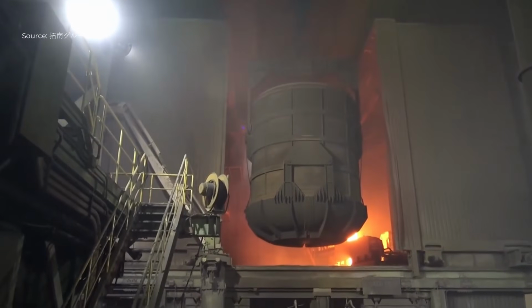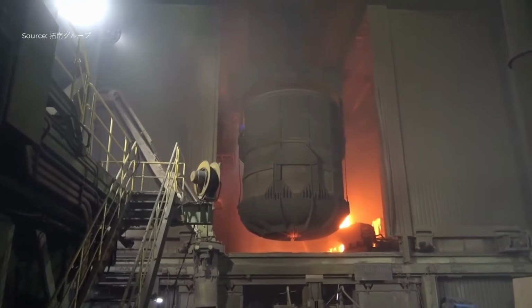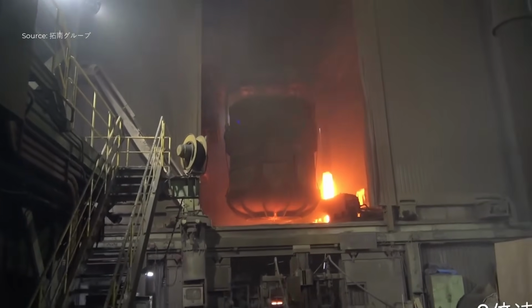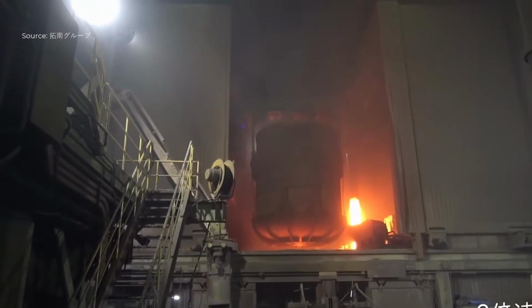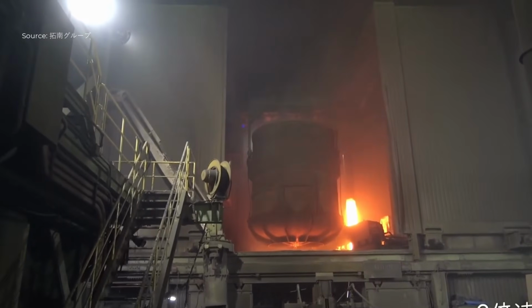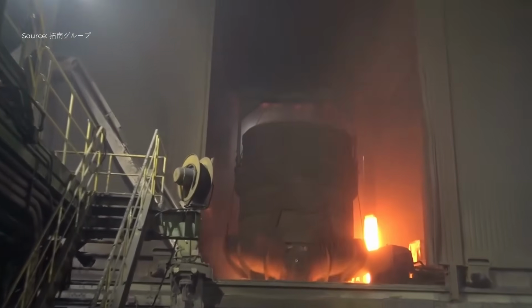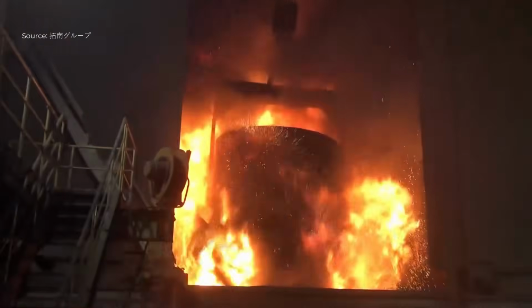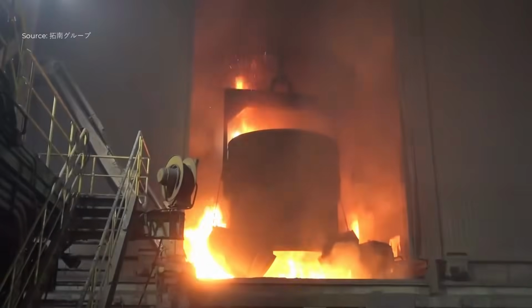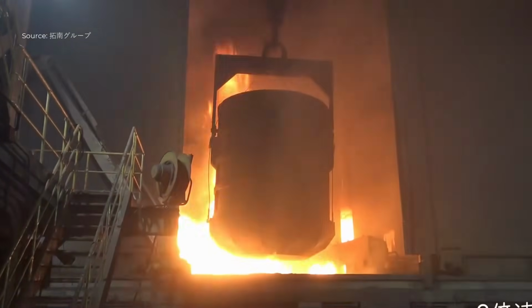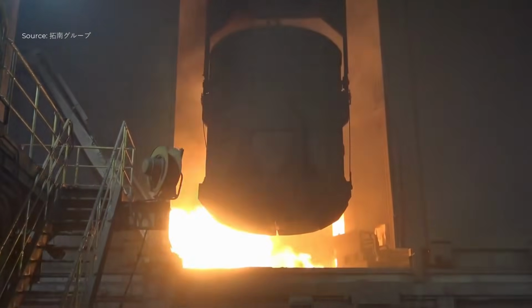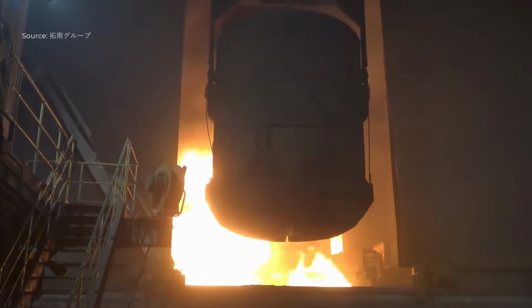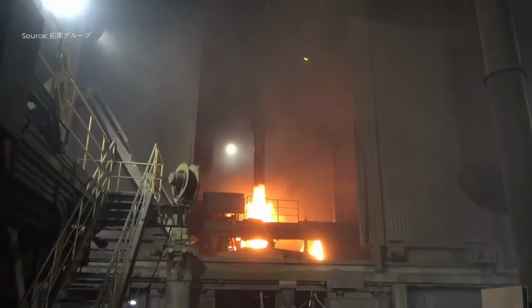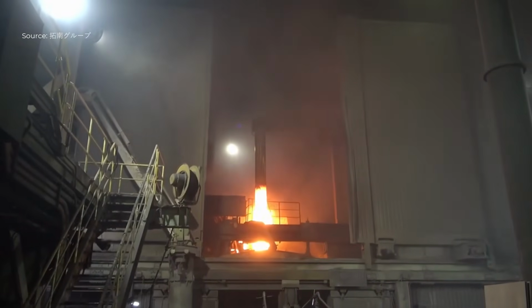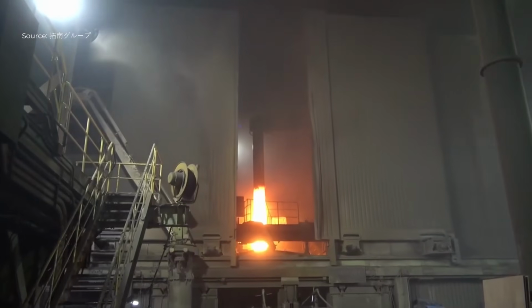In the EAF, high current electric arcs generated between graphite electrodes melt the scrap metal. As the furnace starts, blinding arcs and flames fill the chamber while the temperature rises rapidly to over 1,600 degrees Celsius. Within about 45 minutes, the solid scrap transforms into molten steel. During this period, non-metallic impurities combine with fluxes to form a layer of slag floating on the surface. Workers periodically remove this slag, similar to skimming dross in cooking, to purify the melt. Operators view the process through protective lenses that filter the intense light and heat.